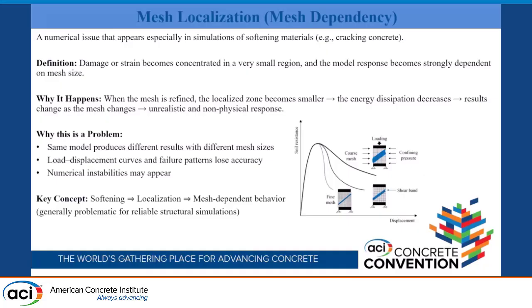This is the problem I was talking about. If you have a strain softening material, physically, it may exhibit a behavior that you're seeing in this load deformation curve where some band of material may fail, which will cause the nearby material to unload, and then the strain will localize, like in slope failures and things like that, and you can get it physically. And that may not be a problem. That might be the physics you're trying to capture.